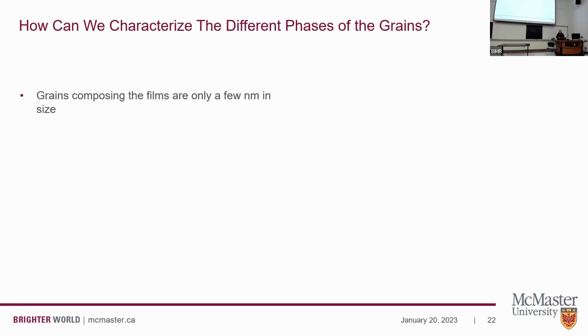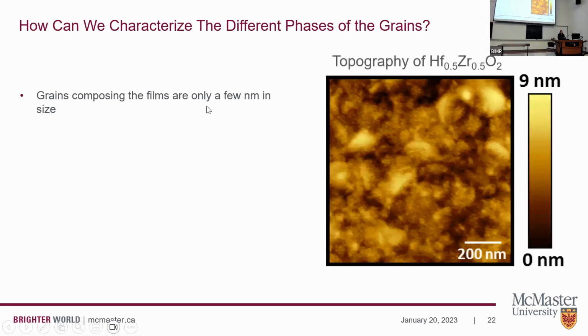So then how can we confirm this hypothesis? Is there any way we could actually characterize the phase in the grains? The challenge is the size of the grains. The grains are only a few nanometers in size. So here is an AFM topography image that we measured on one of our hafnium zirconium oxide films. We can see the grains and they're very, very small, keeping in mind that this is a 200 nanometer scale. So they're very, very tiny.